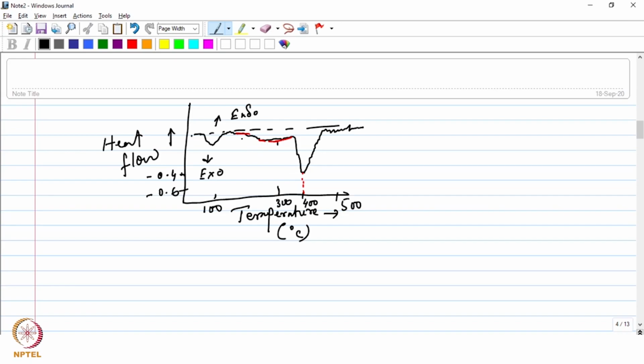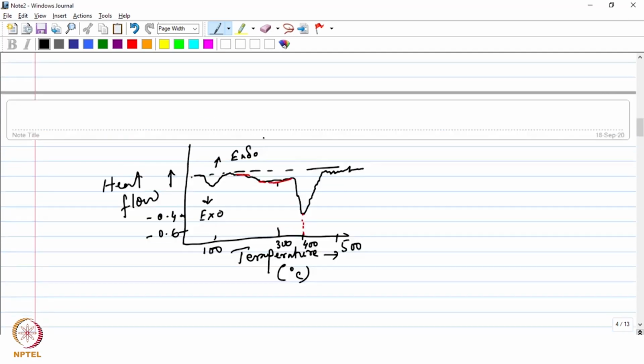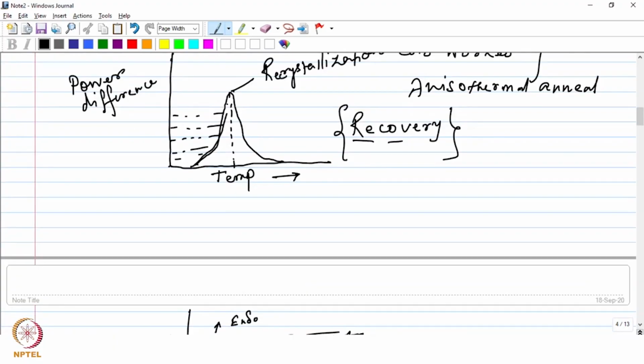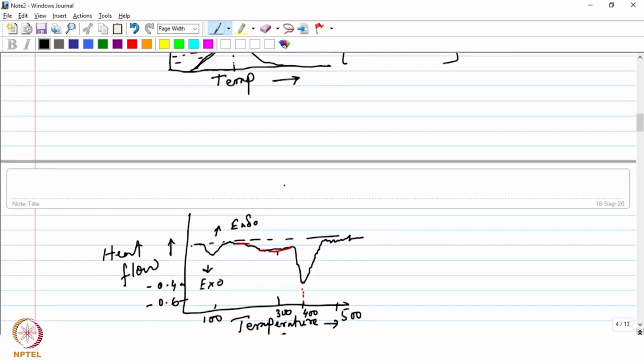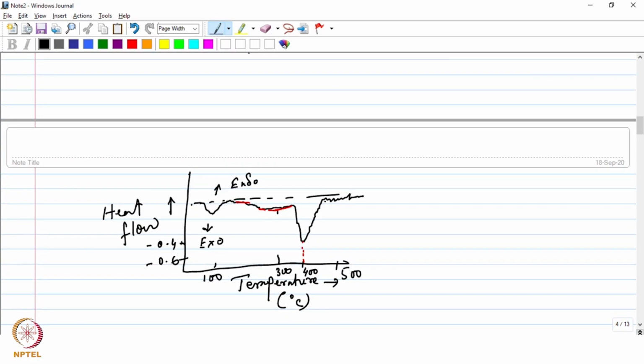So that's what you see when you see these exothermic peaks that indicate the release of energy. And in this case, it is the strain energy which is being released. So during the recovery process at lower temperature, it is a broader peak because you could see that from here also it has just started releasing the strain energy. And then when the recrystallization process actually starts, you have a large amount of strain energy being released, and that is why you see a sharp exothermic peak when the recrystallization process initiates. Okay. So like that, as I said before, you can also visualize this experimentally with this kind of measurement techniques. So now we need to understand as to what exactly happens during the recrystallization process.